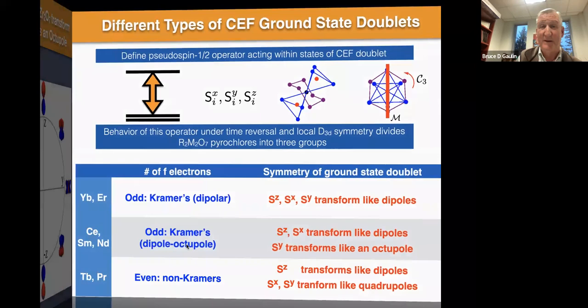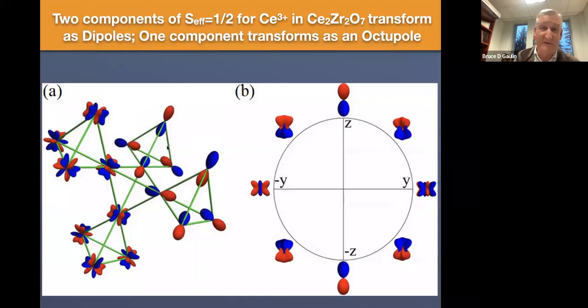And in our case for cerium, it turns out that we've got this dipole-octupole spin-a-half degree of freedom. The way we're going to think about this is not that easy, because we no longer have these little arrows anymore. But we think of the spin-a-half degree of freedom decorating the vertices of a tetrahedron, and two of the components we can think of as acting like magnetic dipoles. So here are some magnetic dipoles that I'm circling with the red and blue extended regions of magnetization density, for example. So these are behaving like magnetic dipoles, and that's relevant for two of the three components.